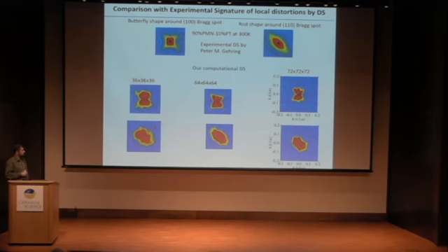And now we see that the butterfly shape slowly grows in. The rod shape also becomes sort of smoother. And so we really think that the discrepancy between experiment and theory is mostly due to just unit cell size. And even at 72 by 72 by 72, I think there is room to improve. But here, I think, we capture the most essential features of experiment.